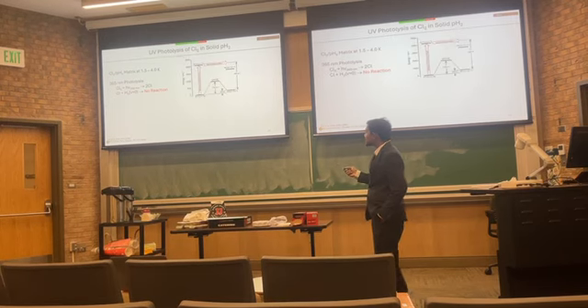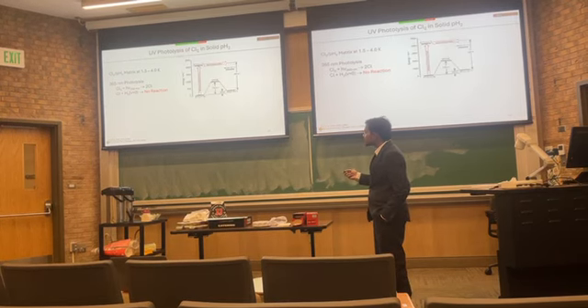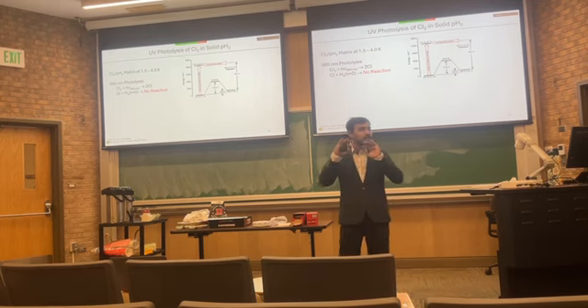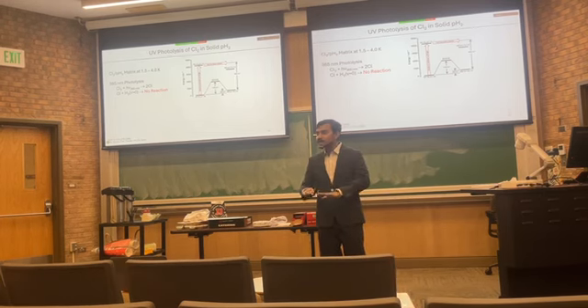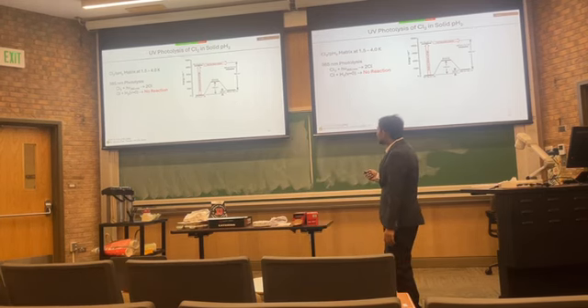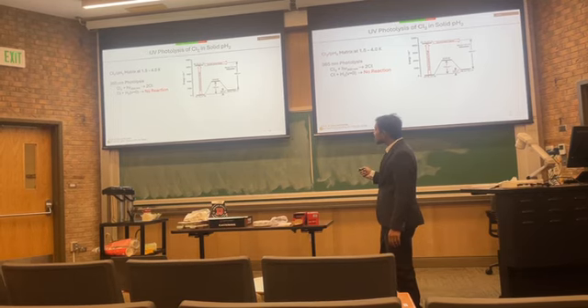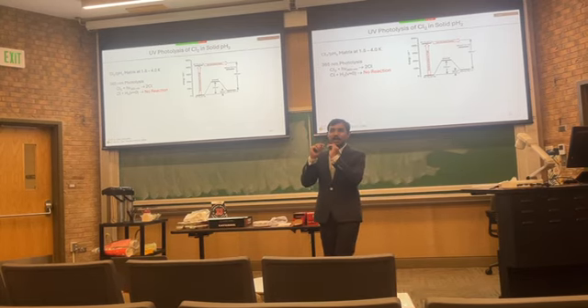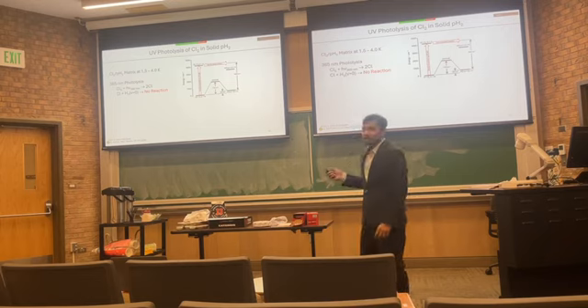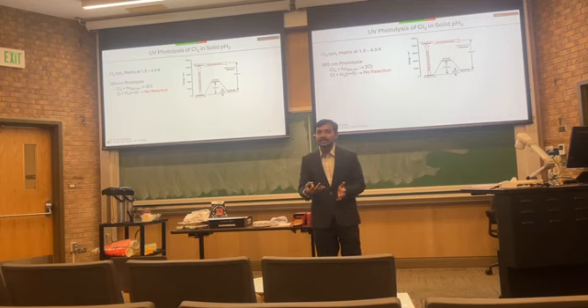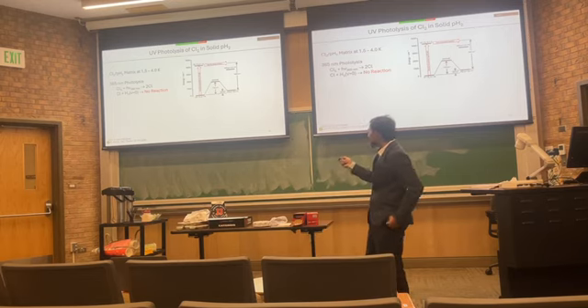Let's look at the energy system. If you have a chlorine atom next to a hydrogen molecule which is not vibrationally excited, in the ground state, it cannot react to make HCl and H atom, because this is endothermic by 360 wavenumbers. It's a very small, tiny bit of energy, but still short. At that temperature, you cannot supply that energy, so this reaction will not happen.